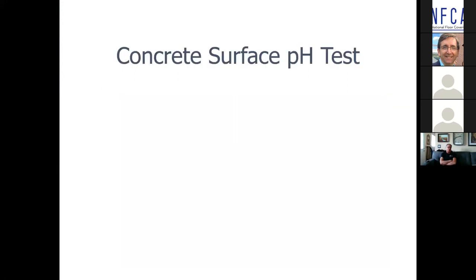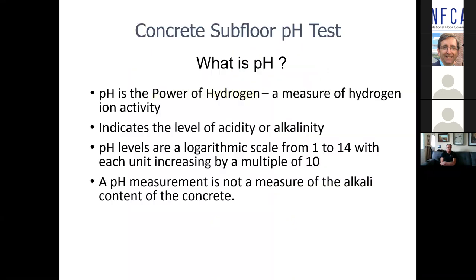Okay. Surface pH test, and this is a real difficult thing for me to talk about because I and many of my colleagues on the ASTM committee believe that, as a pre-installation test, pH testing is a flawed procedure. And why is that? Simply because we're introducing an external liquid source of water that may or may not develop in the concrete itself.